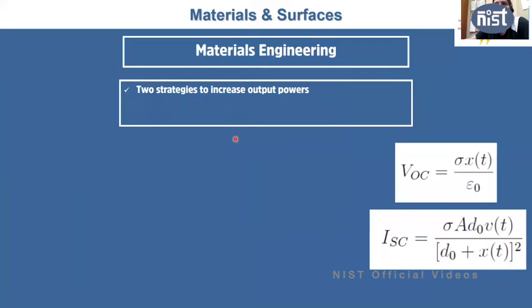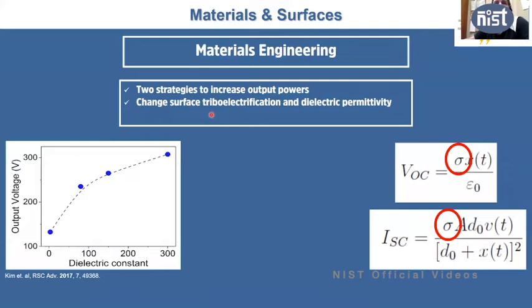And so now you have a standard way to measure this, and you want to change your materials to see how you can improve the efficiency of the energy generation. And you have two strategies to increase these power outputs. The first is you change the surface triboelectrification. So you change the number of surface charges that you can get on a given material. And this can be done by changing the dielectric permittivity, because the surface charge is directly related to the dielectric permittivity, just like in a capacitor.